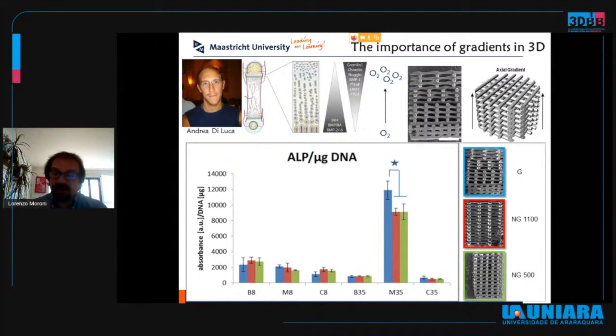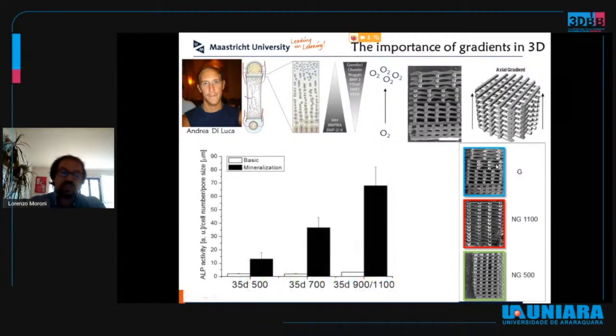If you then cut the gradient construct into the different pore size regions, we would see that such an increase of ALP activity was directly proportional to an increase of the pore size, being highest around a pore size of 900 to 1,100 micrometers, so in the order of sub-millimeter scale.